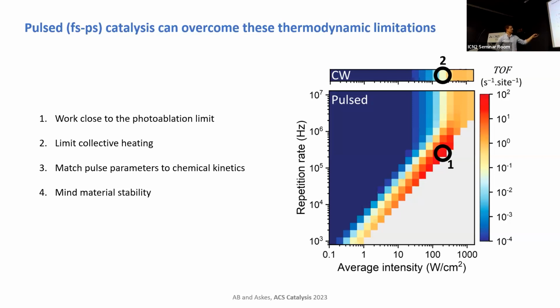We have to be sensitive to collective heating effects. So we don't want the heating to be spread out from one particle to the next. Otherwise, we heat up everything in a steady state. We go back to the steady state, and we don't gain anything from this. We think that there is a lot to gain in playing the right music, playing the right tune of our laser. Because catalytic reactions have a certain rate of adsorption and desorption and product formation. And if we can play with the repetition rate of a laser in order to play the right sound, we think that we can really maximize that kind of efficiency, conversion efficiency.